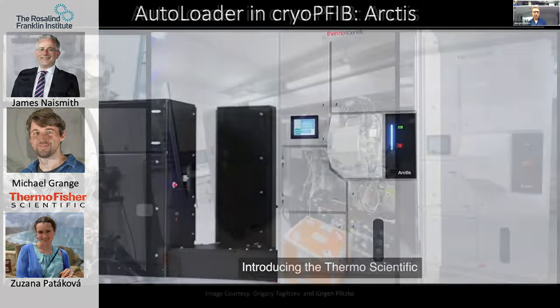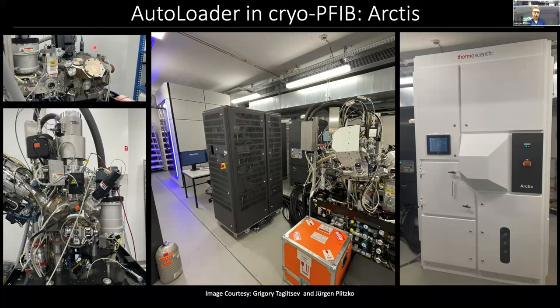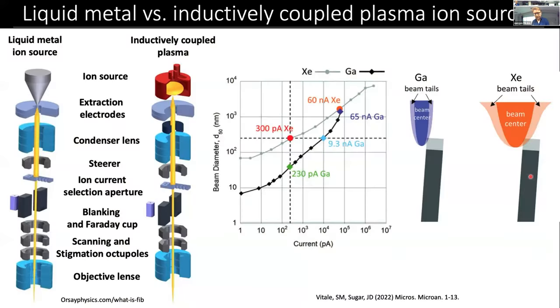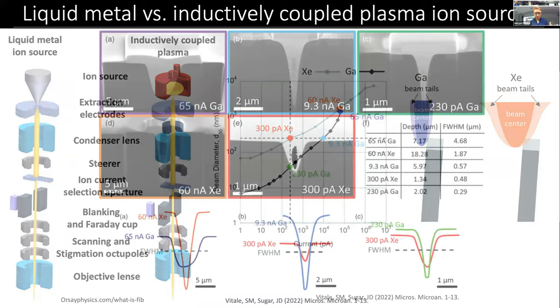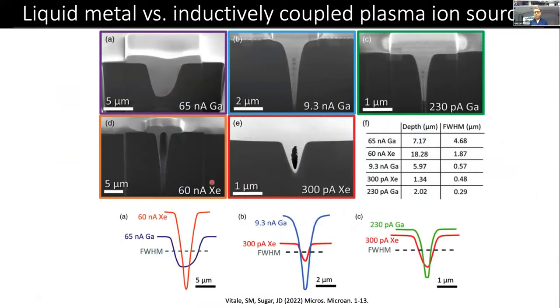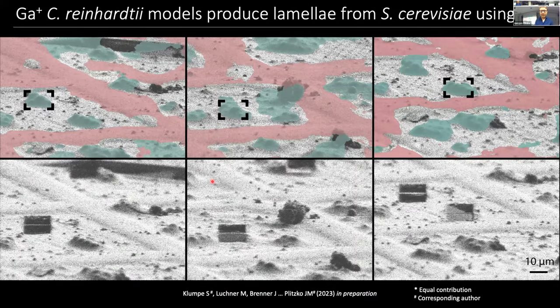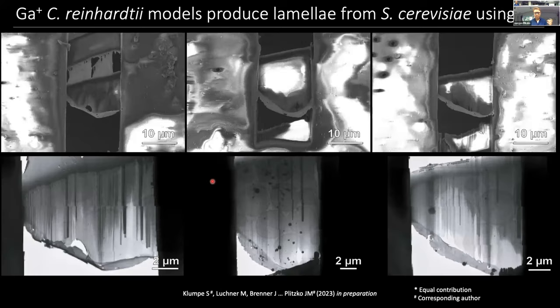And we have one of the prototypes here in the basement, and this is what it looks like. On the left, it's still in the factory, so we have a smaller chamber than the usual models. And on the right now, the fancy, shiny thing. And the main difference of going from gallium-based liquid metal ion sources to xenon-based, as the material scientists have done more recently quite a bit, is that we have different shapes of beams. So basically, at lower currents, the xenon beam is less focused than the gallium beam, while at higher currents, the effect is inverted. However, and this has been characterized quite a bit, we can still use the gallium-based model that we trained on the algae that you saw in Juergen's part of the talk and deploy it on yeast cells using xenon beam milling and still get lamellae out of that model.